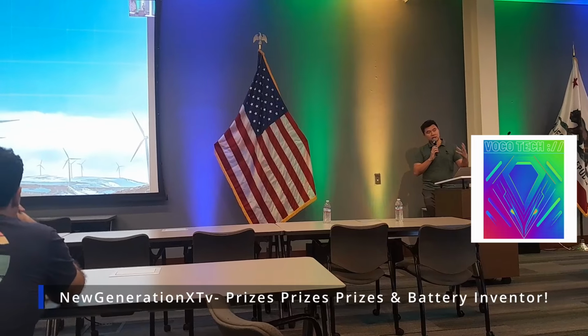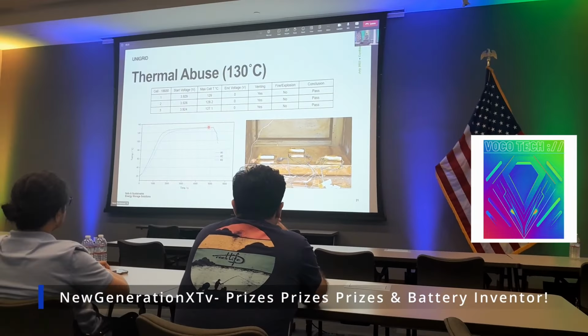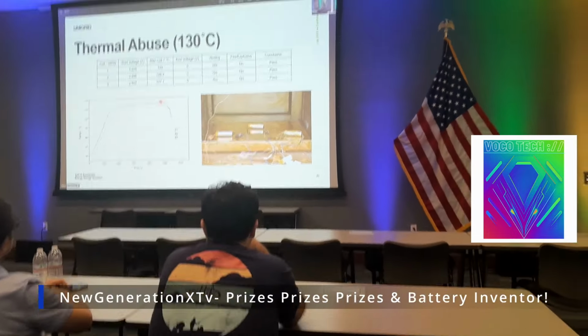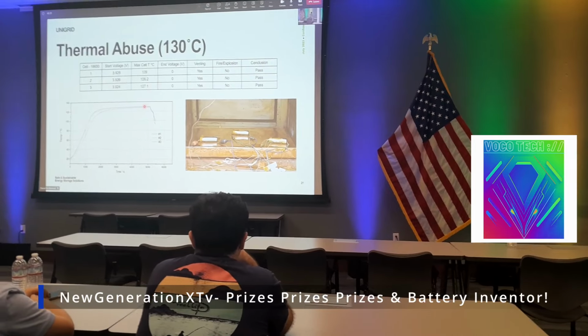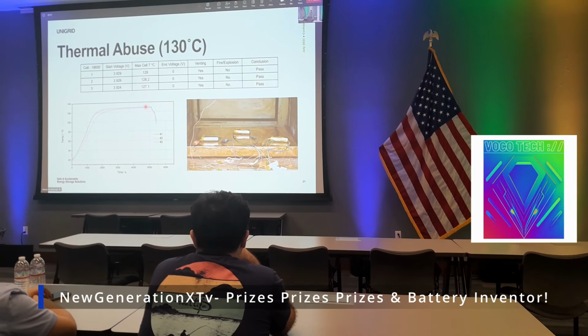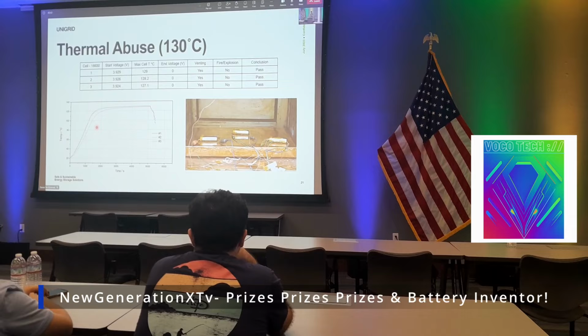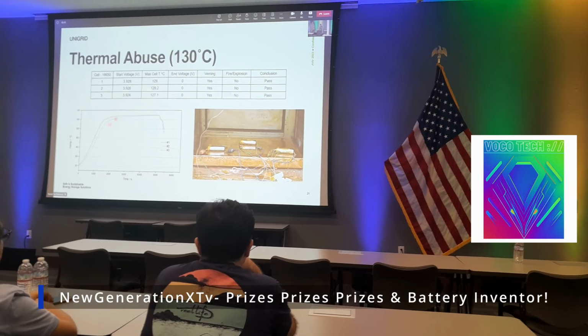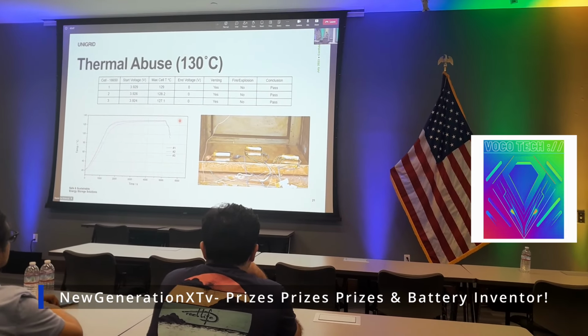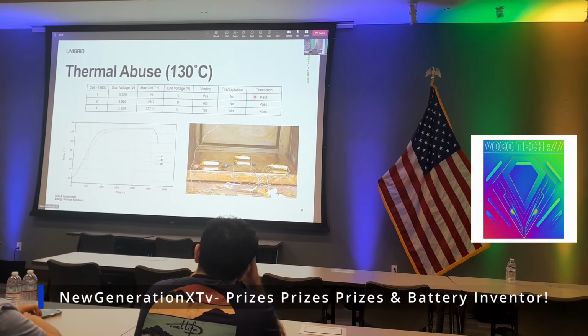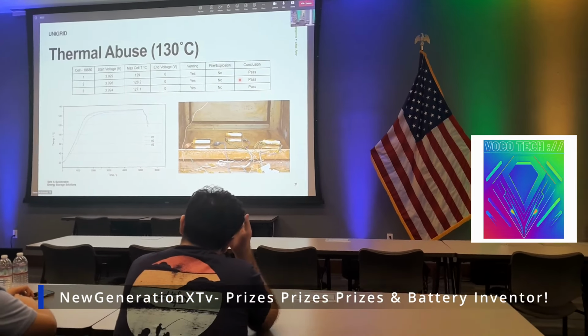Moving on to safety testing, we engaged a third party to do a bunch of safety tests set by the UL guidelines. The first of which is thermal abuse. So what we do is we fully charge the battery and we heat it up to 130 degrees Celsius. Basically, you try to barbecue the battery. When the battery is heated up, you see the temperature goes up and stays at about 130 degrees. And when there's no fire or explosion, we call it a pass. Please don't do this for a lithium-ion cell.